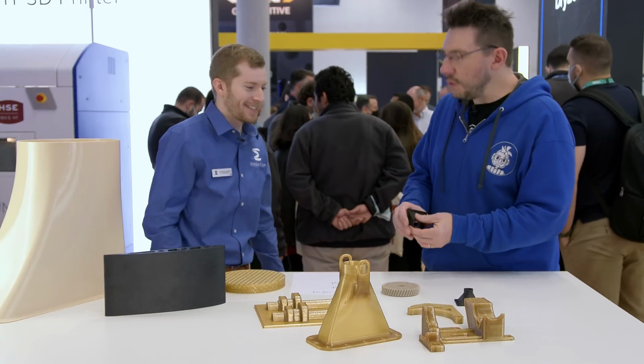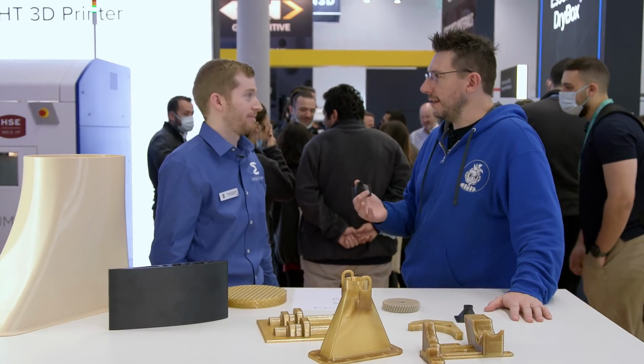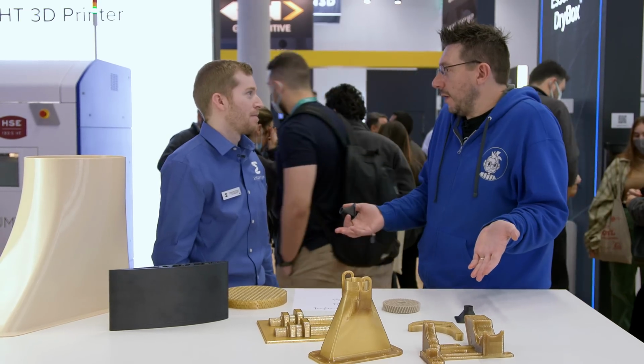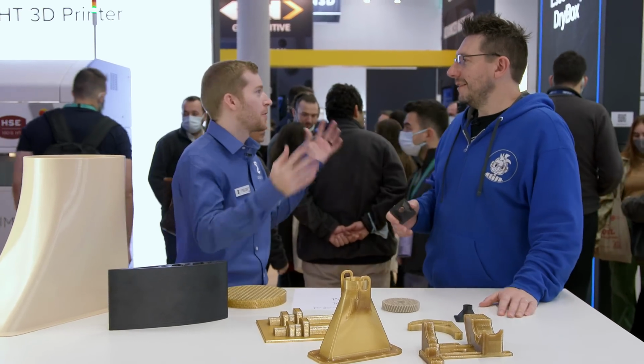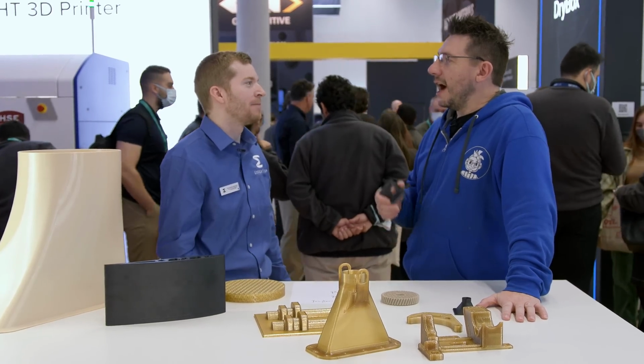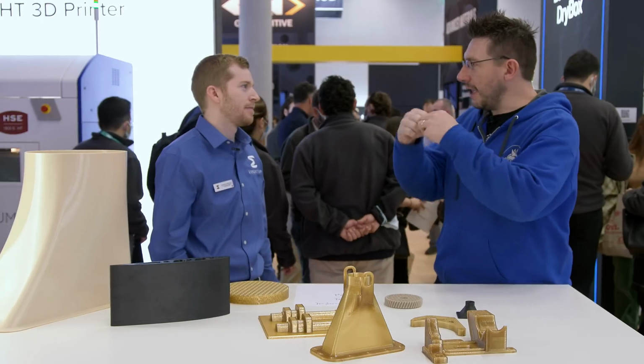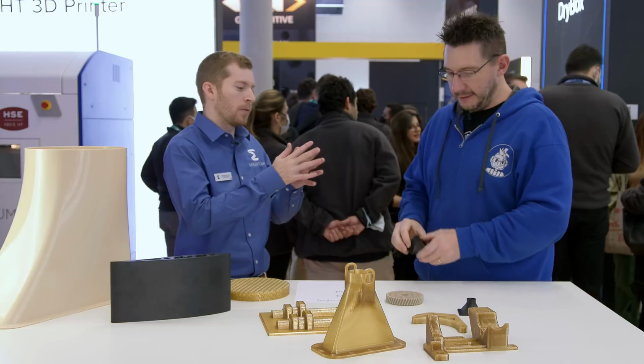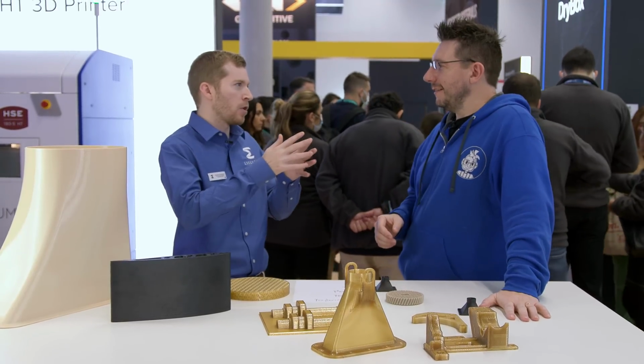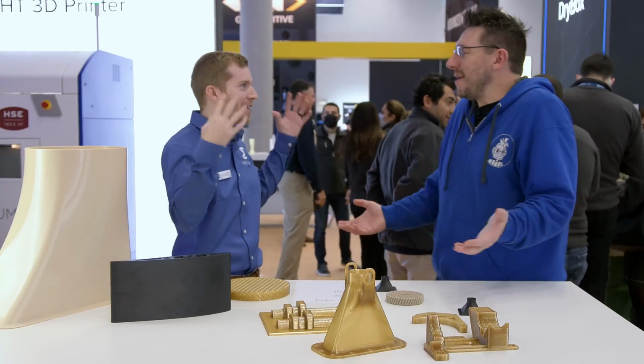What? So wait, you could have a container made of PPS and put hydrochloric acid in it, and it would just shrug and be okay with it, mixed with acetone and chloroform and methyl ethyl ketone? It's just going to blink and be like, yeah, no problem. Unless you heat it up over 200 C, because then it's changing the chemical structures. You're starting to get to the point where the molecules are vibrating a little bit more, there's a little more space, and then the solvent gets in there and it's susceptible. Yep.